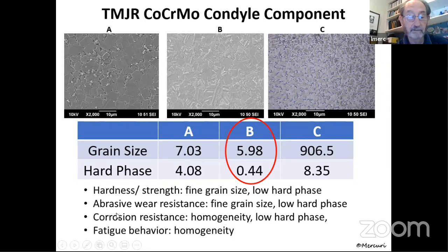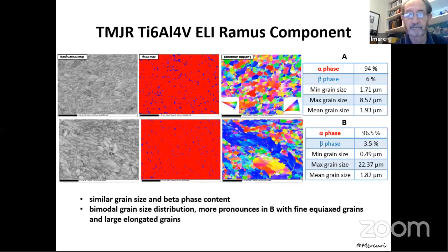And when we're looking at hardness, abrasive wear, corrosion resistance, and fatigue behavior, we want the finest grain structure, the lowest hard bodies. So if you look at these 3, specimen A has a grain size of 7, specimen B 5, and this actually is 1 whole grain of specimen C. So the only one that satisfies us in terms of these variables is specimen B, because we see small grains, we see very, very few hard bodies in here. This one is full of hard bodies and it's 1 giant grain. So that shows the difference under scanning electron microscopy of chrome cobalt condyles. So 3 different companies, 3 different chrome cobalt specimens.